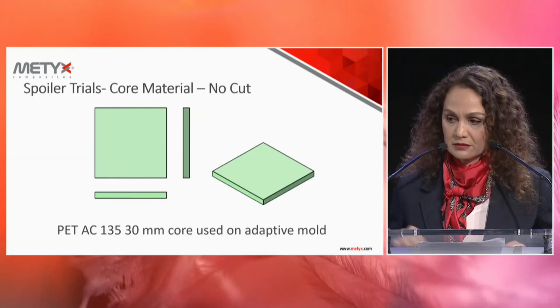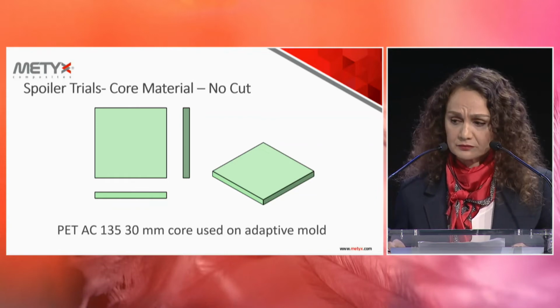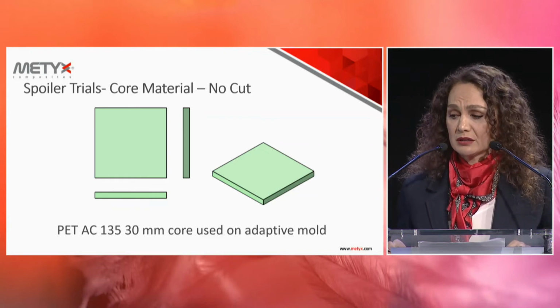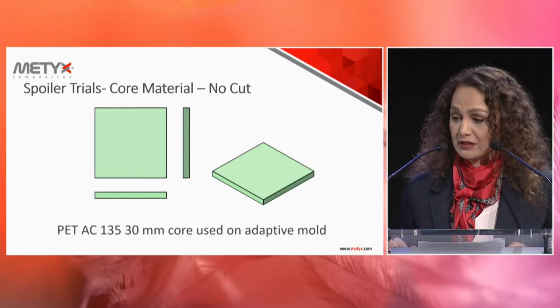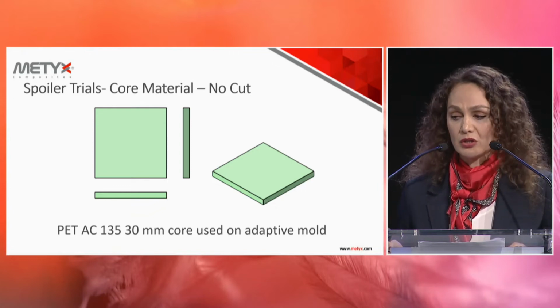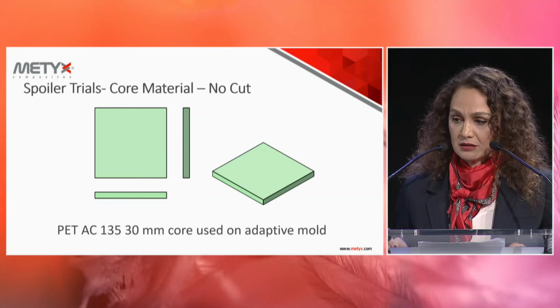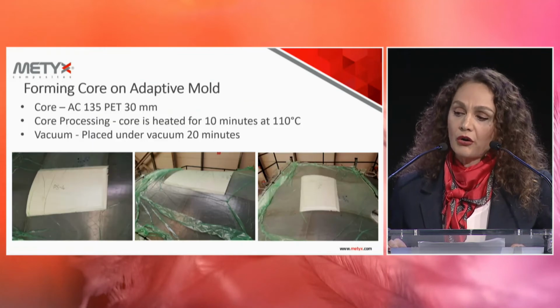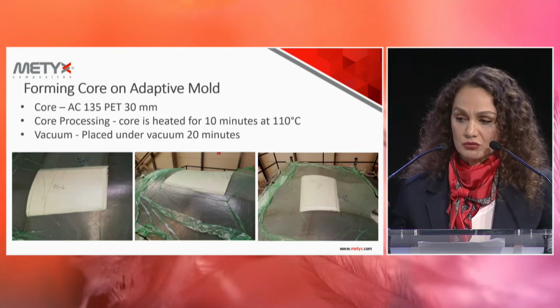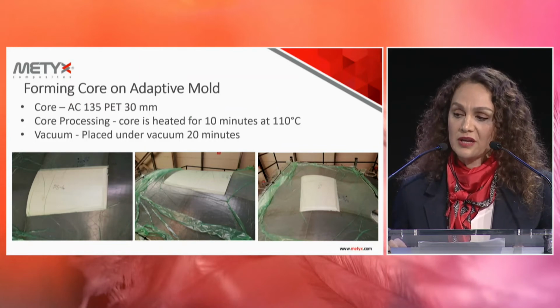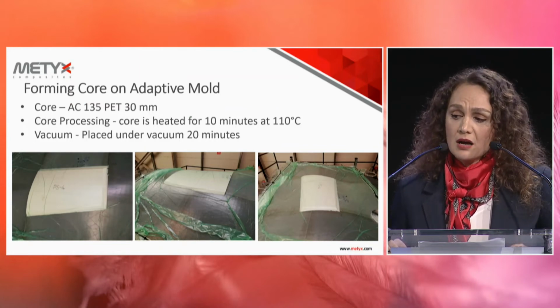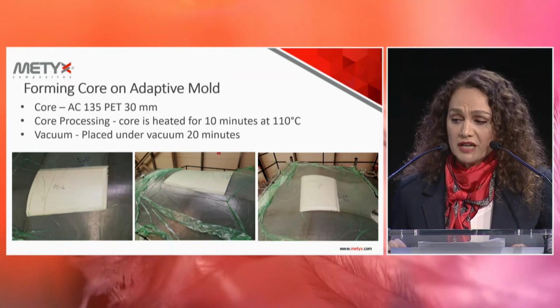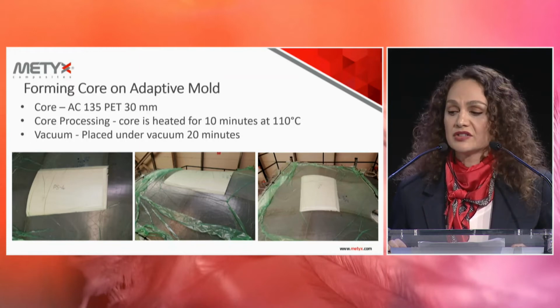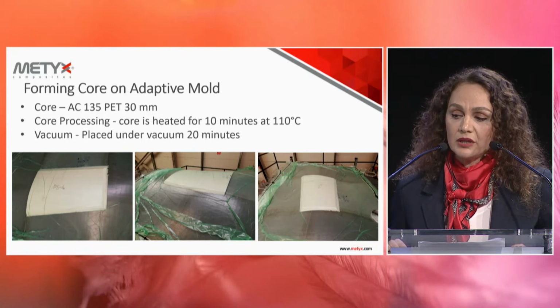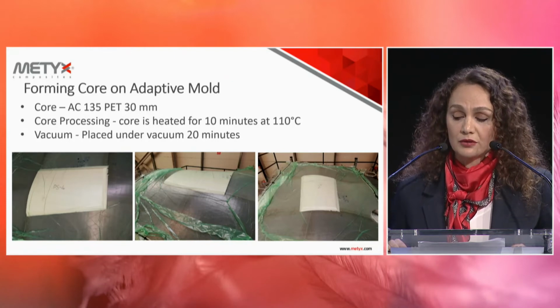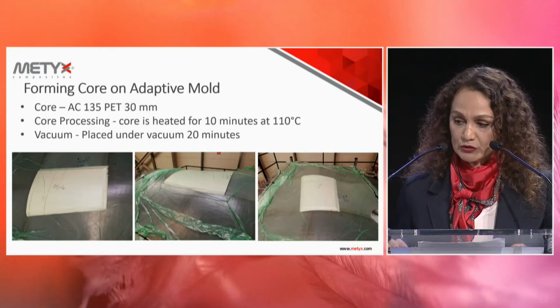So let's get back to the trials again. This is the core we use to shape in the adaptive mold, which has no cut, no groove, or drill on it. For forming the core on the adaptive mold, we use, as we mentioned in the beginning, PET, 30 millimeter thickness. The core is heated for 10 minutes at 110 degrees C. And then after that, we place it under the vacuum for 20 minutes on the mold.